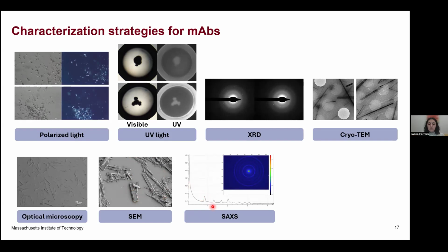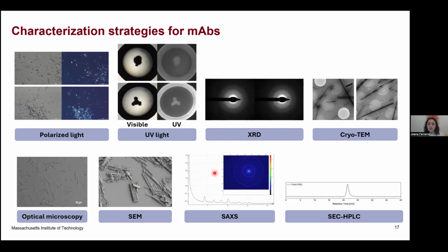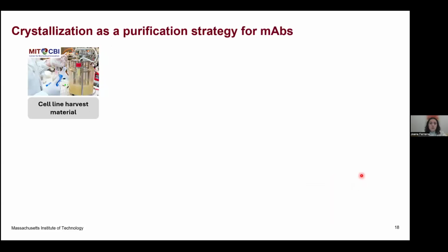We could see the 4 different peaks for this mAb that was in accordance with a paper published by Merck very recently with the same mAb. So we could confirm that in fact we have mAb crystals. And then at the end, we can also wash our crystals, dissolve them, and run size exclusion chromatography to confirm that, again, we have our mAb in solution.